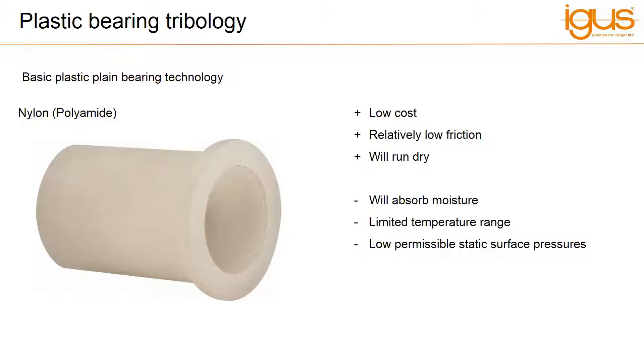Nylon bearings do not require maintenance or lubrication. They are hard-wearing and have low coefficients of friction. However, they do absorb liquid over a prolonged period of time, which can cause swelling and possible seizure in certain applications. Nylon bearings are used in a wide variety of applications all over the world, such as in automotive, machine tools, aircraft, etc. The advantages of nylon and plastic plain bearings are that they are low-cost alternatives to conventional steel-type bearings.